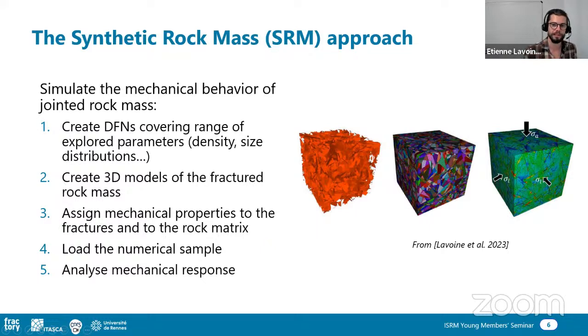But then, since we are interested here in geomechanics, we need to simulate not only the fractures, but also the matrix, which is playing a huge role here. So to do that, we use the synthetic rock mass approach, where we simulate the mechanical behavior of the jointed rock mass by first creating a DFN, several realizations of DFN, covering a range of explored parameters, so several densities, several different size distributions, different orientation distributions, so that we can study what aspect of the DFN is controlling the